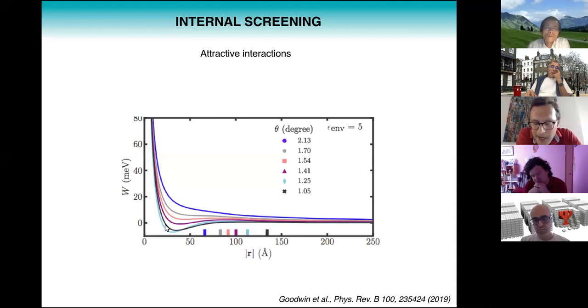Now you might say, attractive interactions are actually not something new. Every material has attractive interactions, every metal, and the reason is of course Friedel oscillations. A Friedel oscillation is an oscillation in real space that is caused by the discontinuity of the Fermi-Dirac distribution in k-space. So every metal, when you calculate the effective interaction from internal screening, has attractive regions. But this is not it, because here we're dealing with a semi-metal. This is undoped graphene, and in a semi-metal there's no discontinuity in k-space. So here we really wouldn't expect Friedel oscillations to be observable.